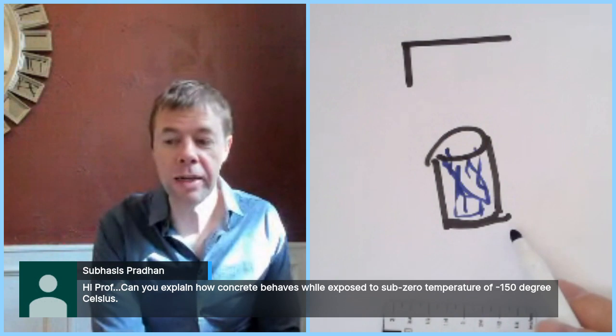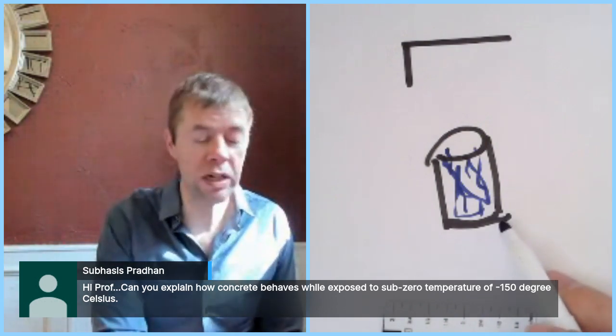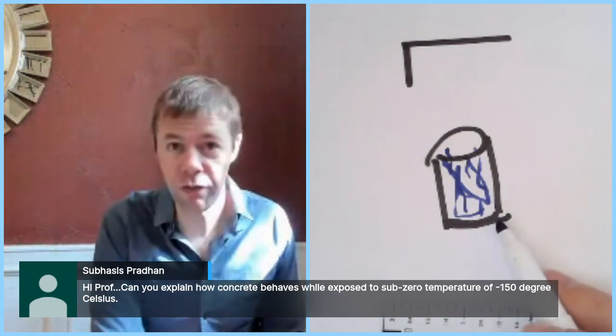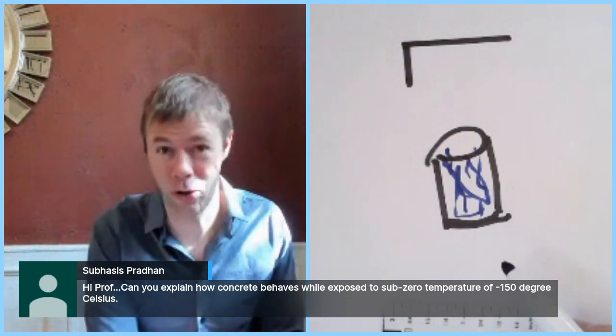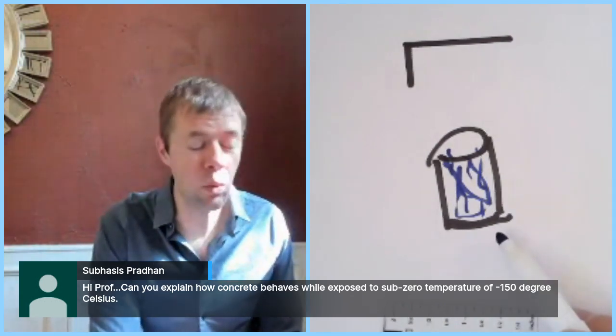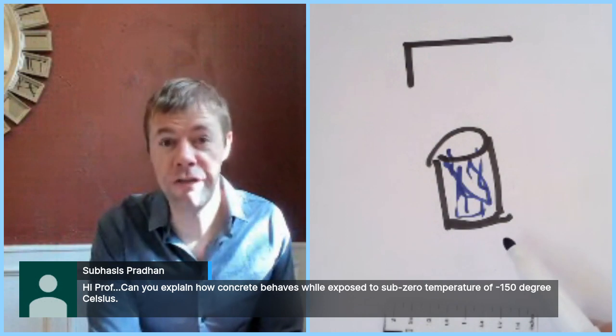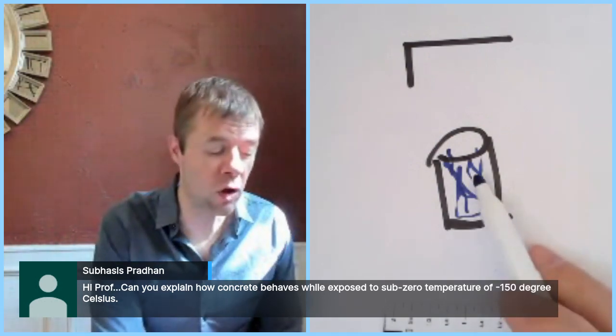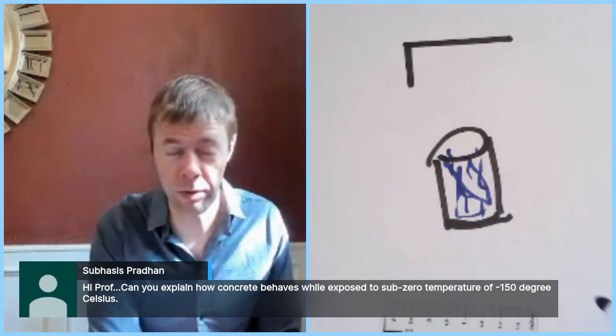And so at minus 150 degrees Celsius, if your concrete is wet and it freezes, it will get a lot stronger. Now you have to make sure it survives and isn't damaged by the freeze-thaw cycles, but it will get very, very, very strong because of all this micro reinforcement that goes inside because of the ice.